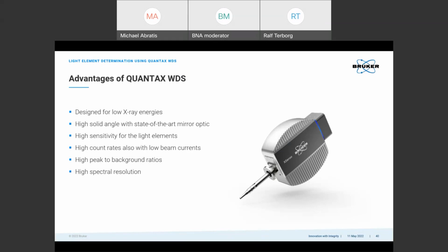EDS is very fast. It allows simultaneous detection of all the elements present, and it can also operate with low beam currents. WDS, on the other hand, has the advantage of providing higher spectral resolution, allowing trace element determination, and it is very sensitive for the low X-ray energies. In conclusion, WDS is ideal to complement the EDS for challenging applications such as light element analysis.